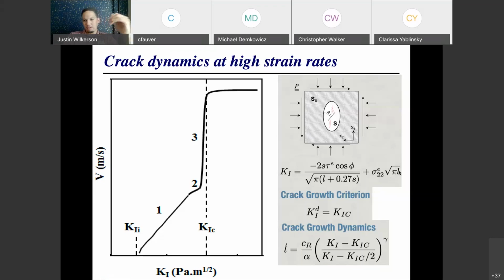Okay, so as the crack grows, the stress intensity factor gets higher, and that's why brittle materials tend to have an unstable failure mode, because you have a runaway instability. As they propagate, stress intensity factor just goes up, the crack moves even faster, and you just get fracture. The criterion for a crack to start growing is generally when the stress intensity factor is equal to a material property called the critical stress intensity factor, K1C, and then the dynamics of crack growth.